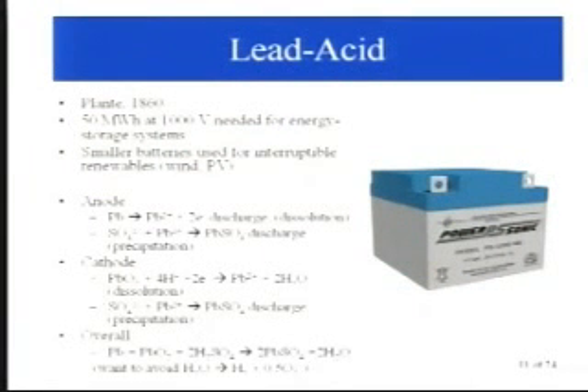Some selected battery technologies, the chemistry. Lead acid is at the anode. You have lead oxidized to Pb2+, and on the discharge. And at the cathode, you have lead oxide. These are the reactions, and both form this precipitation of lead sulfate. And so this is the overall reaction, but generally you'd want to avoid gassing.